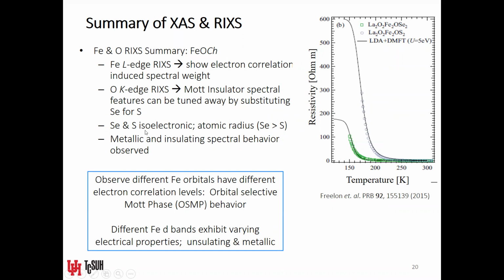Now, both of those atoms are isoelectronic, and the atomic radius of selenium is actually greater than sulfur. Our resistivity measurements, however, show us that the resistivity of the selenium compound is less than that of sulfur. So these resistivity measurements do not behave in the way that band theory suggests that they should on the basis of atomic radii.